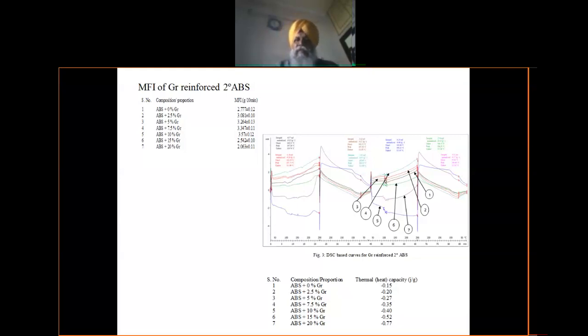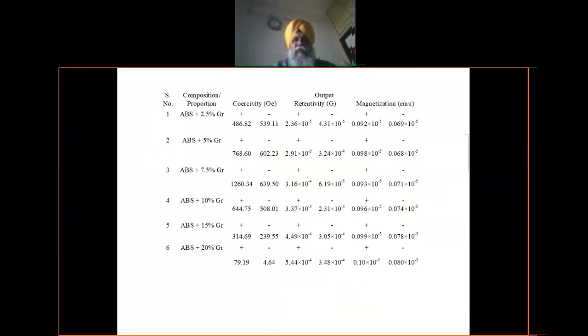So then in the second stage, we again go for the thermal analysis of that material. Like it will be more clear from here. So once I add 0% graphene, means there was no graphene, the energy capacity was 0.15 joule per gram. So this minus sign is the heating cycle. So this much, 0.15 joule per gram, was the energy absorbing capacity. So once I am increasing the composition of the graphene, the heat capacity or the thermal capacity was basically increasing. So I can have a particular quantity of the graphene in my ABS, based upon my requirement in the thermal analysis, right? I can control basically how my material is going to perform in what type of environment for making that sort of an antenna, right?